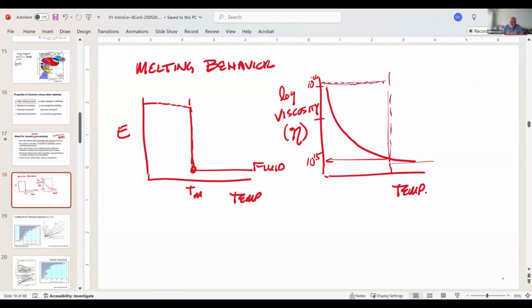There's this folklore I mentioned before, and it's sort of the standard joke. In old buildings, you find that the windows are typically thicker at the bottom. And the question is, why is that the case? And the argument is, oh, the glass flows. Actually, it's not quite true. They put the thick end down. So this is false. The windows are thicker at the bottom, yes, but not because of viscous flow. By the way, if it was, all your skylights would be bowed in.